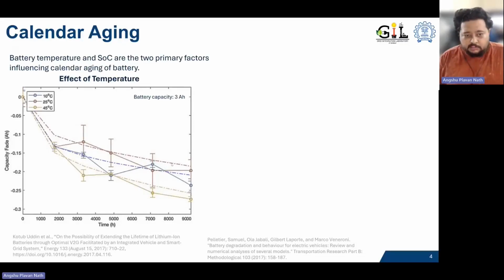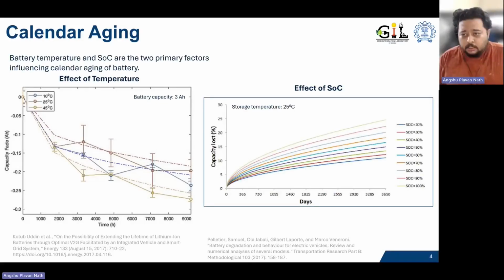So just like human beings, batteries like to be stored at normal operating ranges between 20 and 30 degrees Celsius. If we store at much lower temperatures, even then the life of the battery is impacted. Next, if you look at the SOC, as I mentioned earlier, depending on the SOC at which you store the battery, your degradation will be higher. If you store a battery at 20% SOC, the degradation is much lower compared to if you store the battery at 100% SOC.